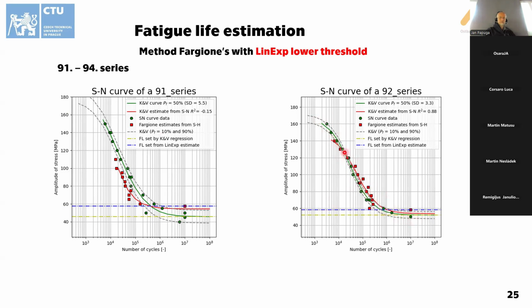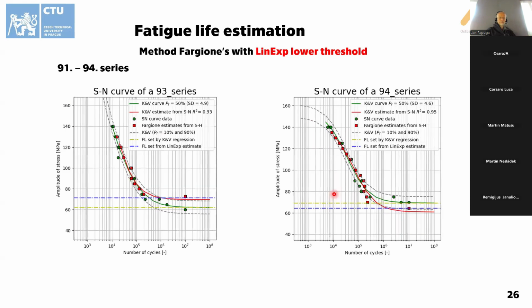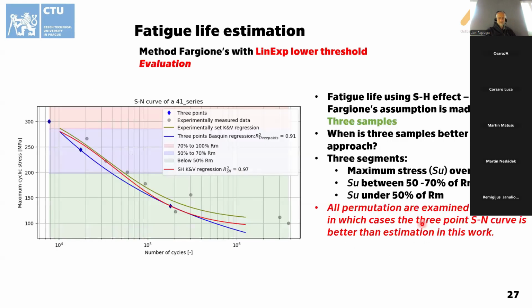If you look at other publications, this is really good. Basically no outliers, and so we don't fit in the 10 to 90% of probability of failure. For the 93rd, you can see we were able to mimic the SN curve really well. However, the LinExp approach did not work well in this case, and we are too optimistic. For the 94th, we are pessimistic, but for any possible construction use of the LinExp approach for the industry, to be conservative is better in this case.